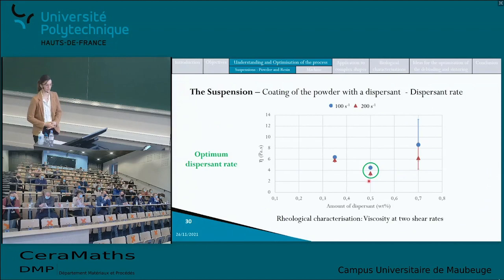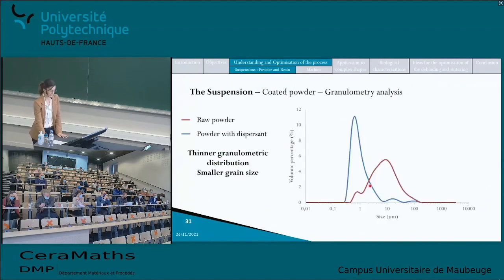I did the granulometry analysis of the coated powder in order to compare it to the raw powder, because the grinding media also enables to deagglomerate the powder. And I, in fact, realized that there is a thinner grain size distribution of the powder that can help with the sintering process. So I decided to pursue the experiment with this coated powder.